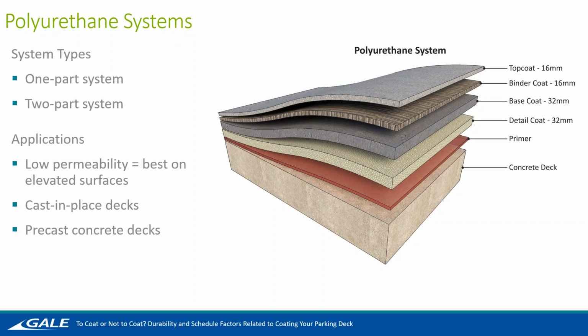It was 75% solids, and the curing was based upon the atmosphere and the moisture in the atmosphere. So as you probably think, it took a while for it to cure. And then with that came the 2-part system. They addressed the flaws with the 1-part system. The 2-part system is 100% solids, and it cures a little faster. It still uses the atmosphere and the weather conditions around to cure, but it was a lot faster than the